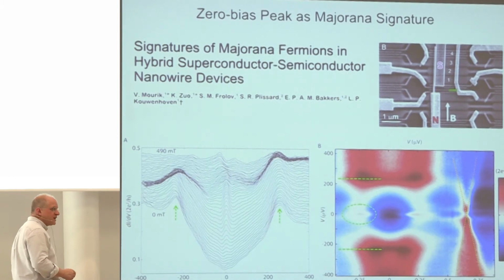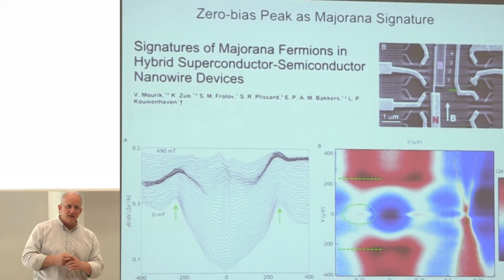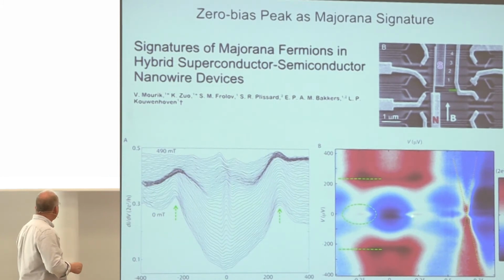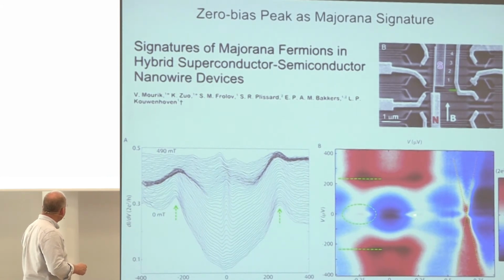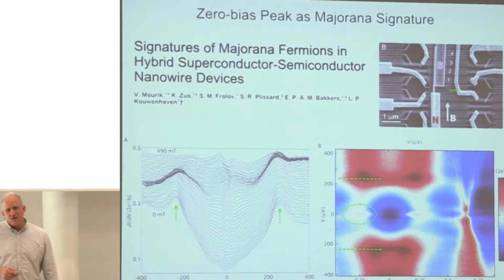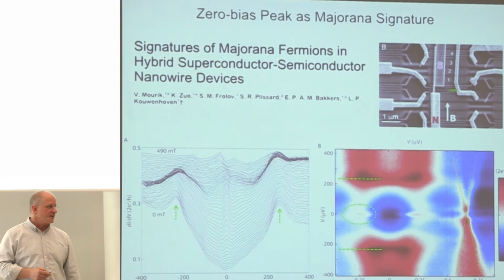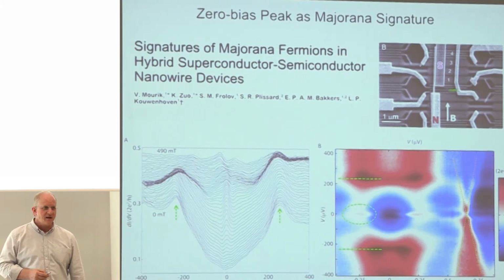As you turn up the magnetic field to a value which is roughly the Zeeman splitting in indium antimonide equaling the gap, a peak would appear, and the peak would appear at this value of magnetic field. And you would have liked, of course, for the peak to have persisted up to higher magnetic field, and God knows what all of this stuff is, but in any case, a peak appeared right at the right value. And like a typical experiment, it didn't look like a plot of theory, but it looked like it had a lot of the key signatures. And the paper went on to study the orientations in magnetic field and really rule out a lot of alternatives, and came out with a very bold claim, which was that these so-called elusive Majoranas are evidently not that elusive at all.